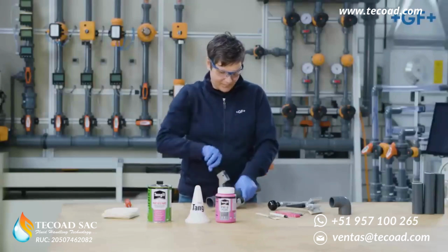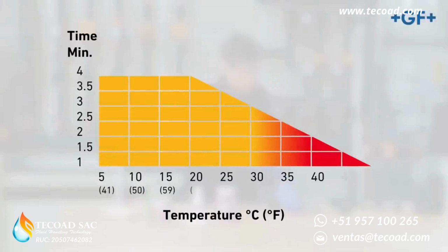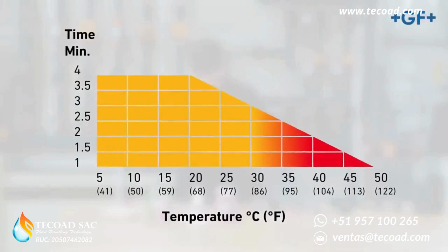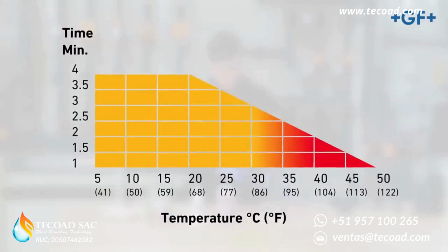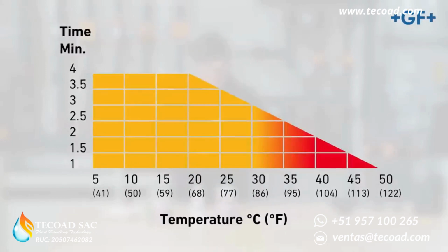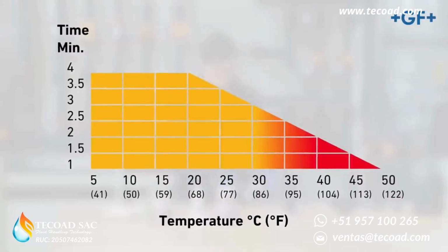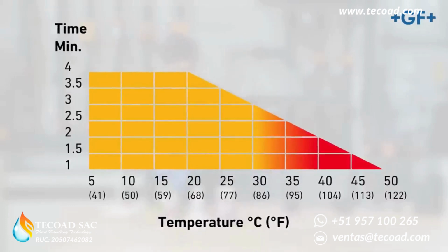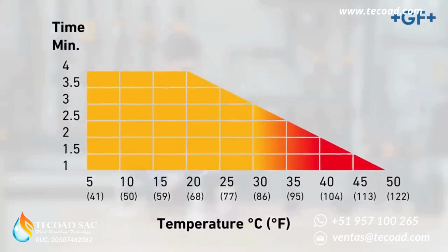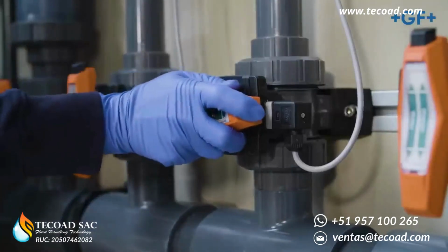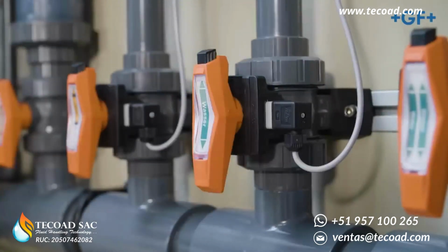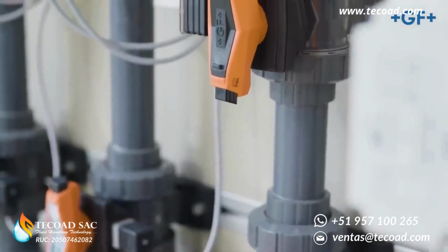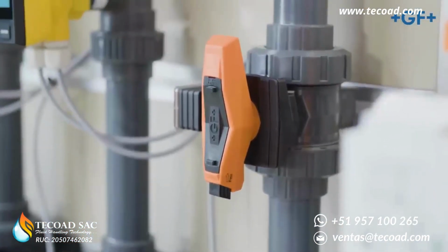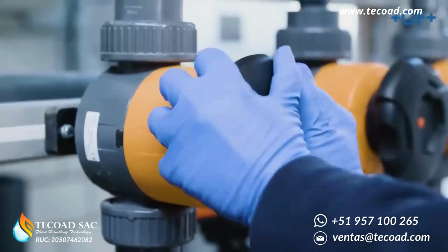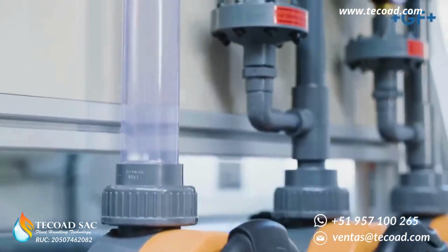It is important to proceed swiftly during the jointing process. The open time of the cements varies, and at a temperature of 20 degrees Celsius and film thickness of 1 millimeter is between about 1 minute and a maximum of 4 minutes, depending on the cement used. This period decreases in the case of higher temperatures or a reduced film thickness. Installed pipelines and valves should be left open, allowing any solvent fumes to escape the system. The pipes can be filled after the drying process. Before startup, the pipelines must be flushed thoroughly to remove any solvent vapors that may still be present. Compressed air must not be used as a flushing medium.